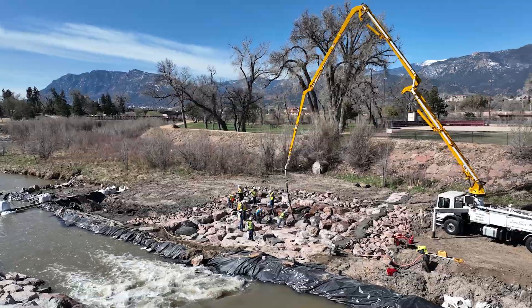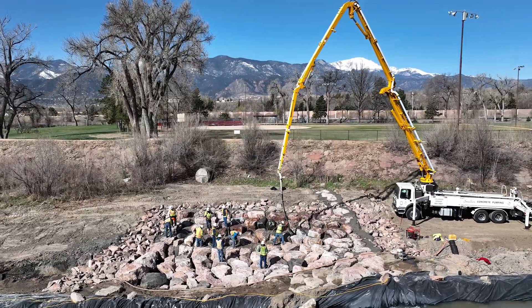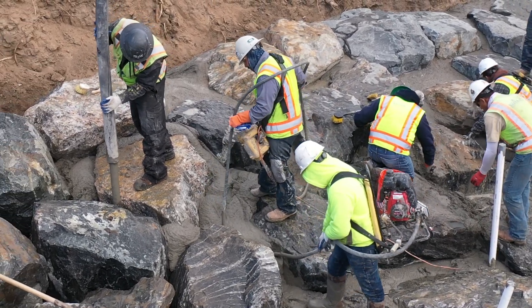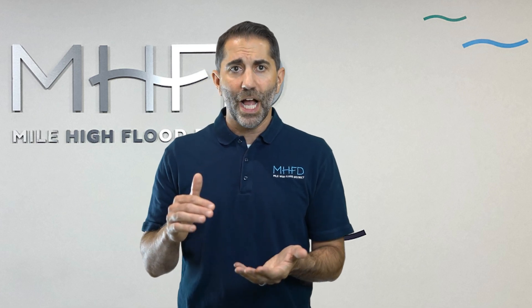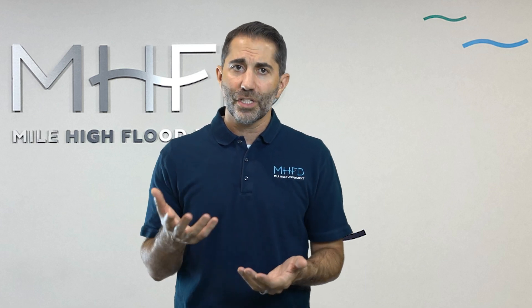Grout is typically delivered with a pump using a 4-inch nozzle. Usually a concrete pump truck is utilized for its long reach and convenience of having a remote-controlled nozzle that can be manipulated by hydraulics. Grout should be injected starting with the nozzle near the subgrade and raising it as the grout fills in. Small grouted boulder installations may make use of a concrete bucket in lieu of a pump, but this method is typically not productive enough for use on larger structures where cold joints could form because the pour takes too long. Grout should be vibrated in place using a mechanical pencil vibrator to consolidate the grout and remove any air bubbles. Grout should be placed so that it completely fills all the voids between the boulders. Grout thickness is typically specified as half the boulder height but no more than two-thirds the boulder height. Keeping the grout level low and leaving more of the boulder height visible improves the appearance, but be sure to consult the design team for any project-specific aesthetic requirements.